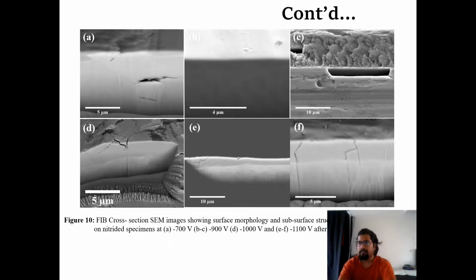And here we can see E and F as well as D. These are basically 1000 and 1100 volt, where most of these cracks are within the nitrided layer and are flowing deeper inside the substrate, which shows that these shear cracks as well as fatigue cracks are not good from the application point of view.